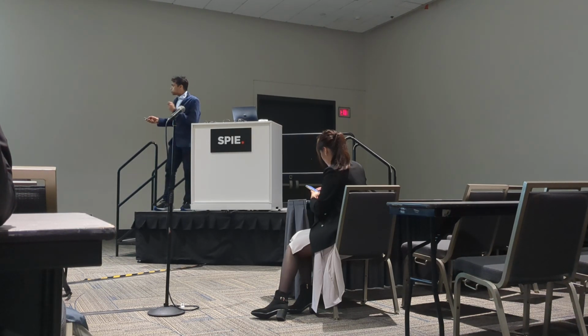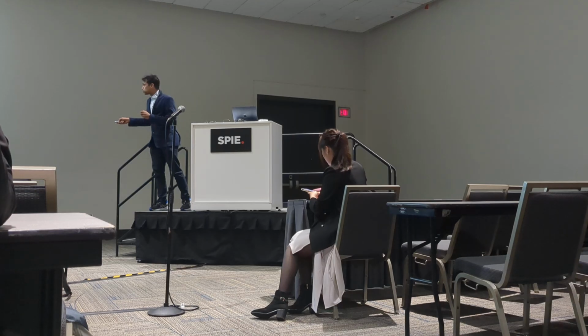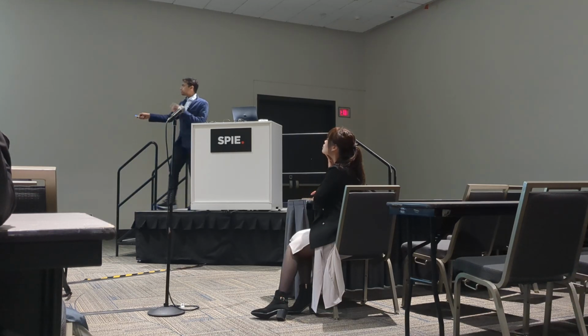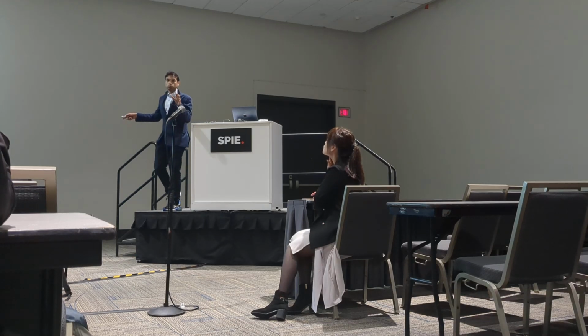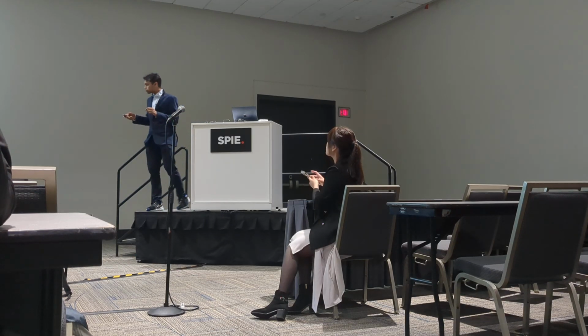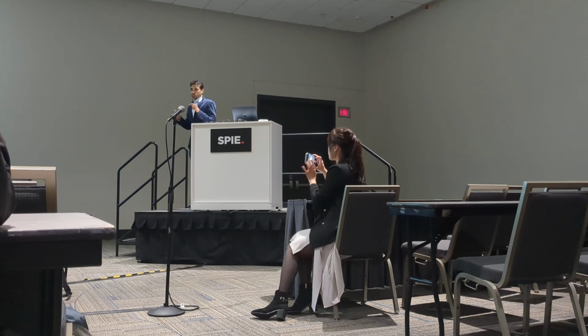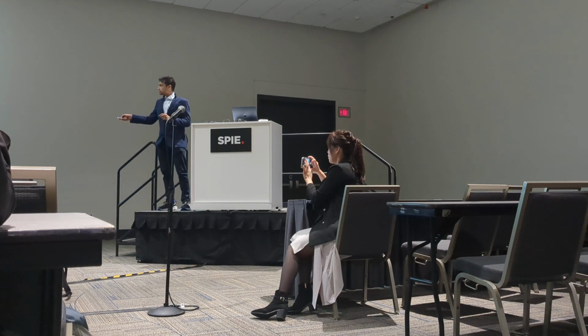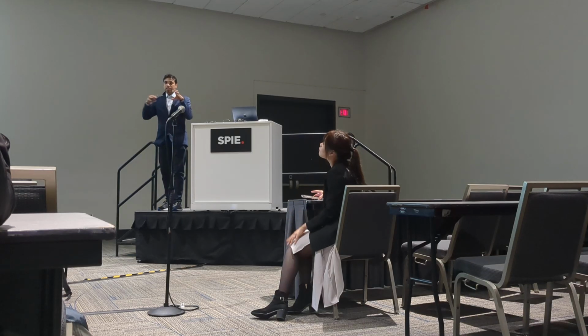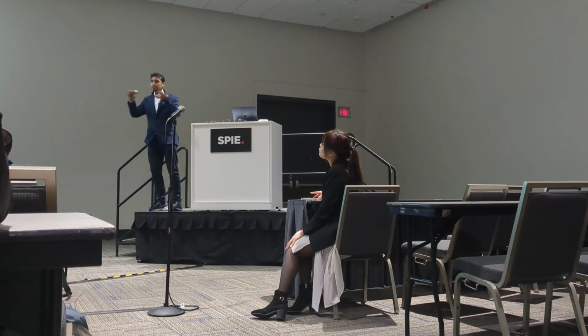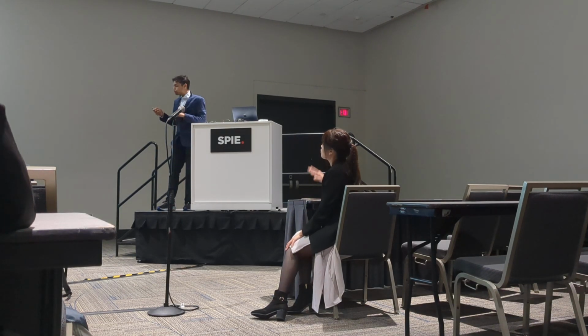Now, the takeaway message from this slide is that it is the presence of oligomers that causes gallium to engulf into the substrate, and there are different other properties which result because there are oligomers in the PDMS. So from here, what we understand is that the structure is gallium droplets. They are spatially static to each other, and they are embedded in a matrix of PDMS.